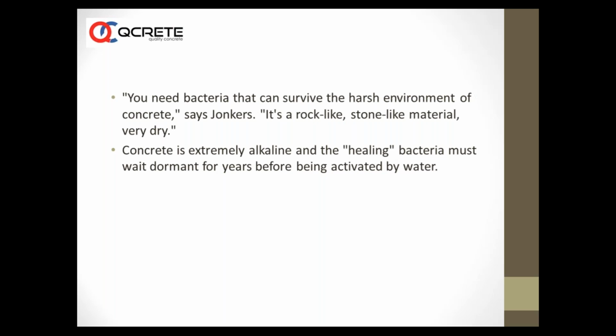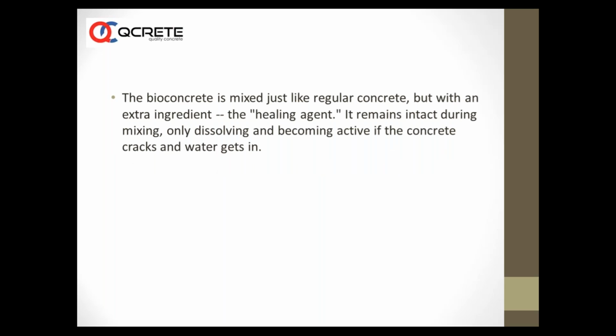He said you need bacteria that can survive the harsh environment of concrete, and concrete is extremely alkaline. Healing bacteria must wait dormant for years before being activated by water. So the technology is you have some bacteria, it gets encapsulated in some capsules, you add it as an admixture along with the concrete while you are making concrete, and then whenever the crack opens, when the oxygen enters, water enters, it reacts, breaks this encapsulation, reacts with the bacteria, and the precipitation of calcium carbonate takes place, and you have these cracks healed actually. So that is the principle.